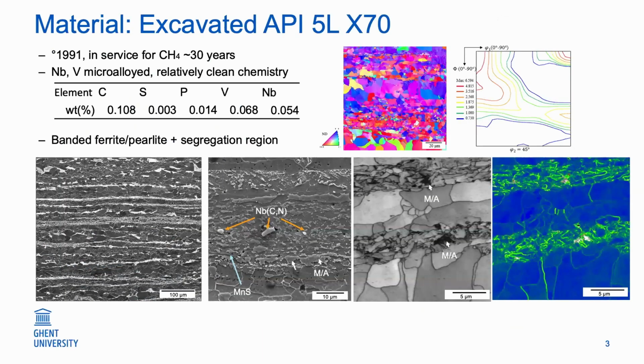Specifically, I worked on X70 grade pipeline steel, which was actually in service for 30 years as a natural gas pipeline, and was excavated. And we're looking at actually a quite modern, or at least relatively clean, relatively low carbon, niobium vanadium microalloyed steel with a nice rolling texture, mostly banded ferrite pearlite, but also in the center we can find a quite pronounced segregation region where we can find some different microstructures, and very specifically some harder microstructures. So we're looking at bainite, martensite, austenite islands, and also very large niobium precipitates, and some elongated manganese sulfide.